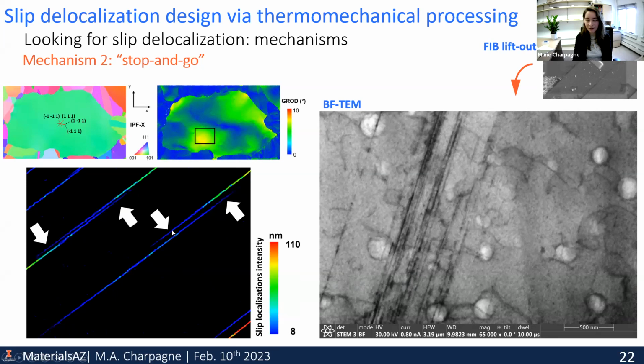We can think of either cross slip from one slip band to another, which is kind of difficult to tell from how untangled these slip bands are and how compact they are. But that could be one mechanism. The other mechanism that we're thinking about is activation of a second source of dislocations just nearby the first slip band, so, like from the bottom of the material or the bottom of the grain, a second source that gets triggered to emit another slip band. So this is still unanswered. It's a very tough question to answer, but I think the fact that we see these kinds of mechanisms is very promising with respect to fatigue.